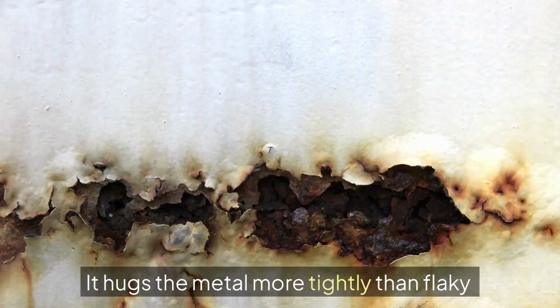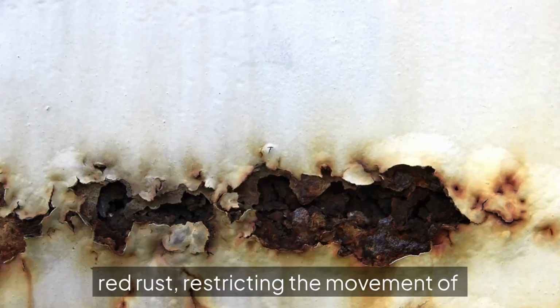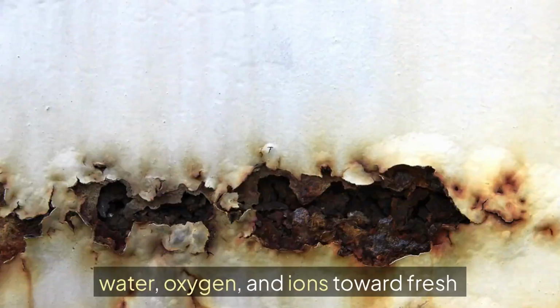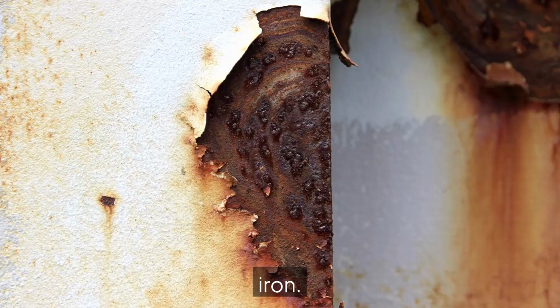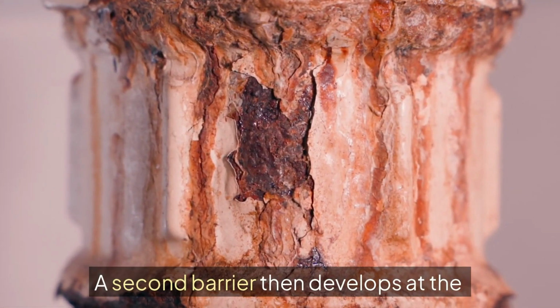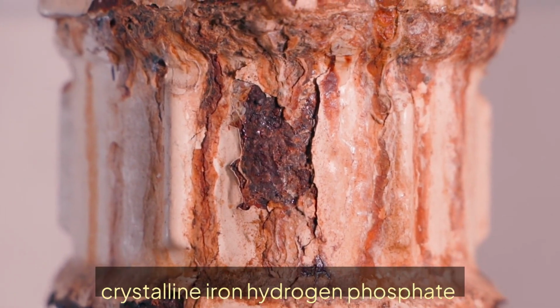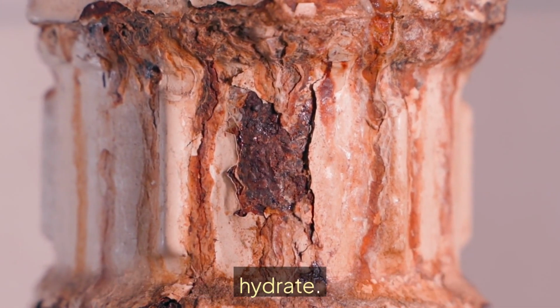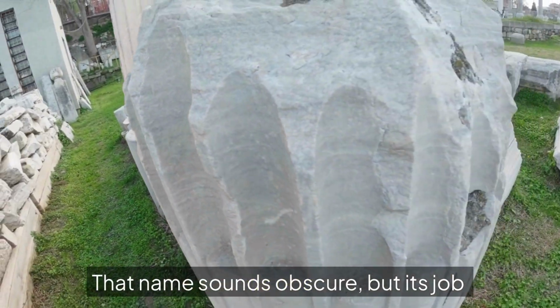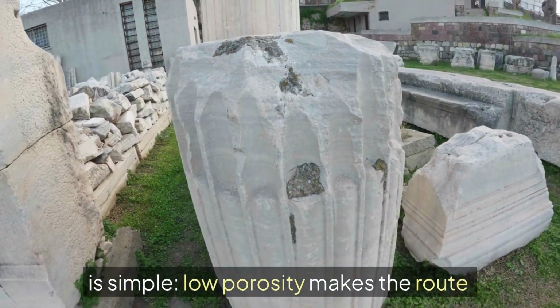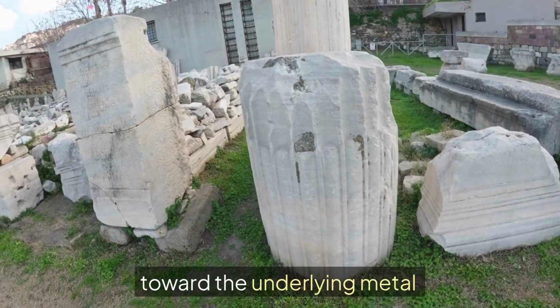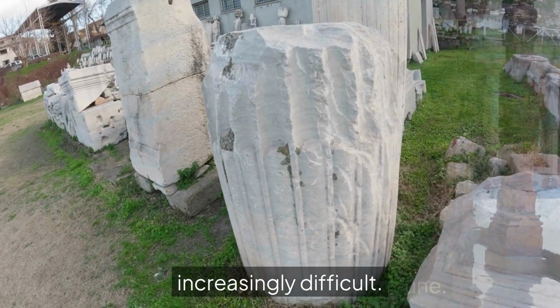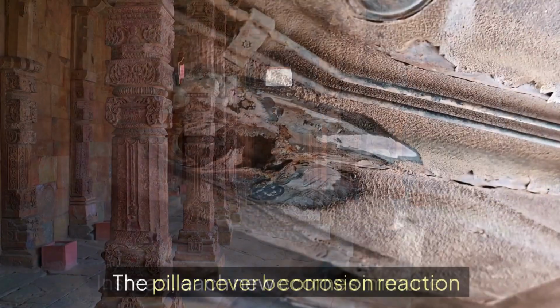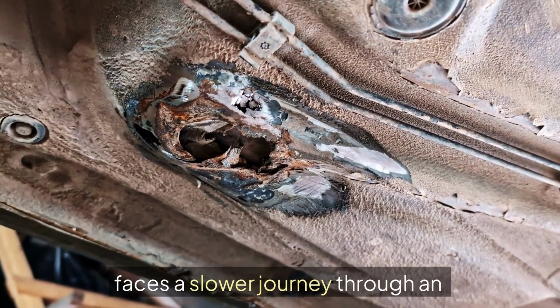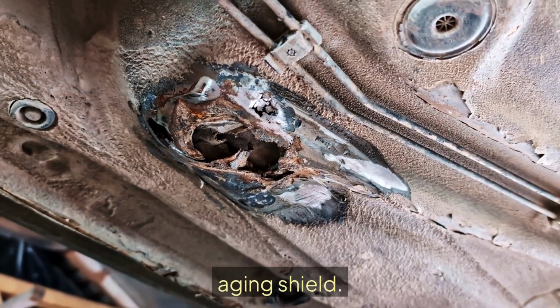It hugs the metal more tightly than flaky red rust, restricting the movement of water, oxygen, and ions toward fresh iron. A second barrier then develops at the metal-rust interface, containing crystalline iron hydrogen phosphate. That name sounds obscure, but its job is simple. Low porosity makes the route toward the underlying metal increasingly difficult. The pillar never becomes immune. Instead, each new corrosion reaction faces a slower journey through an aging shield.